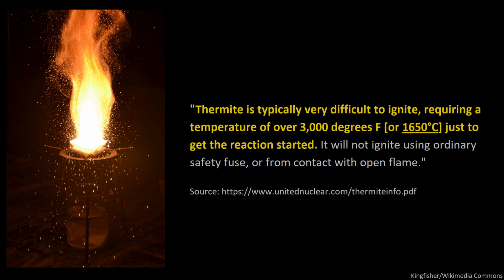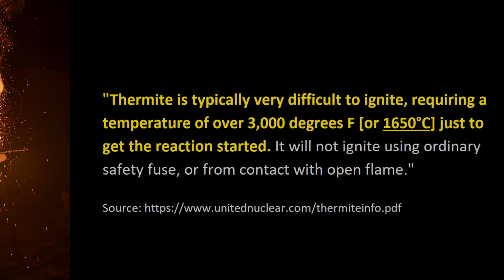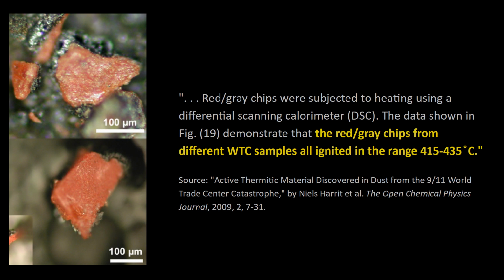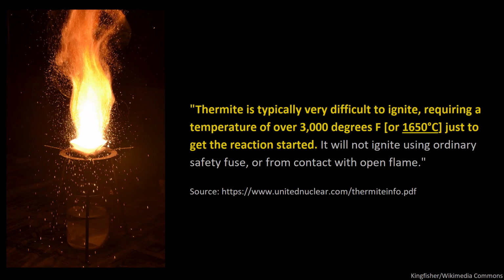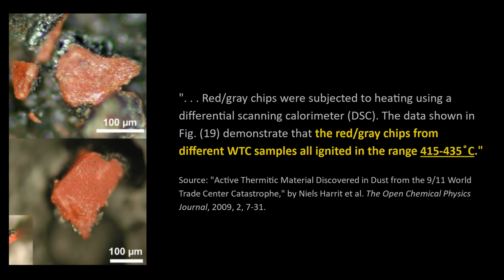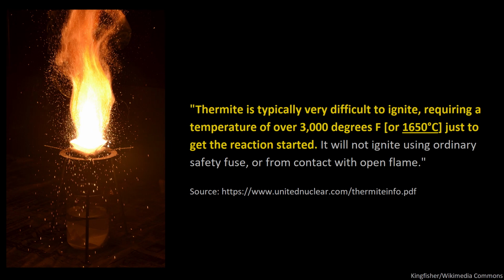So to start a thermitic reaction requires temperatures in excess of 1600 degrees Celsius. The red-gray chips ignited at temperatures as low as 415 C, almost 4 times lower than that required to start an actual thermitic reaction. If that's not a checkmate right there, I don't know what is. Once again, what they're claiming is proof of thermite is actually proof of the opposite.